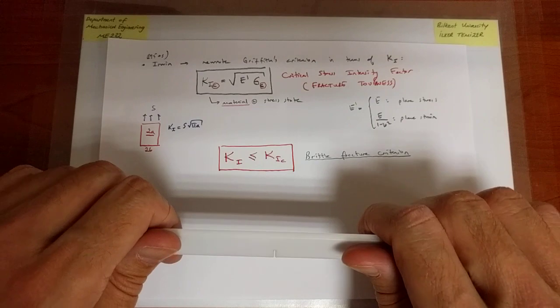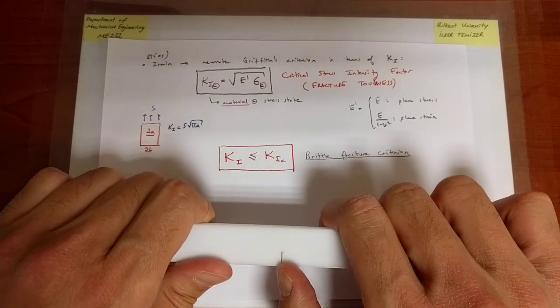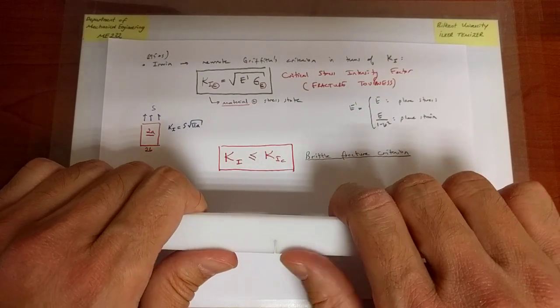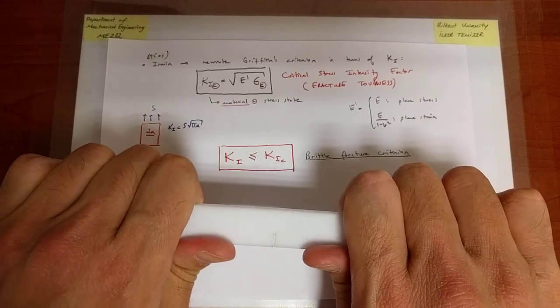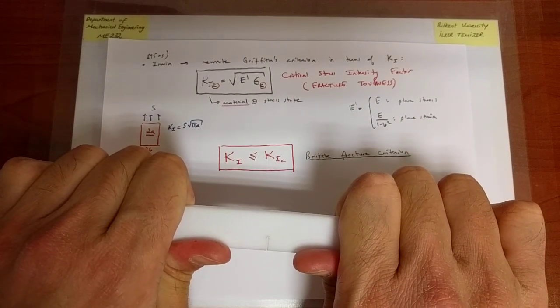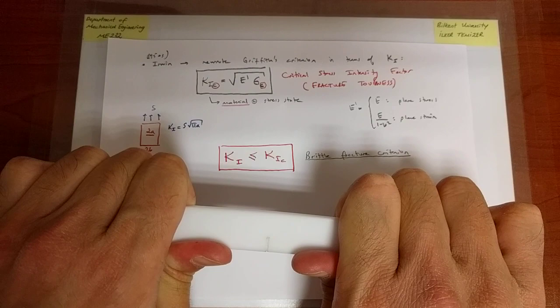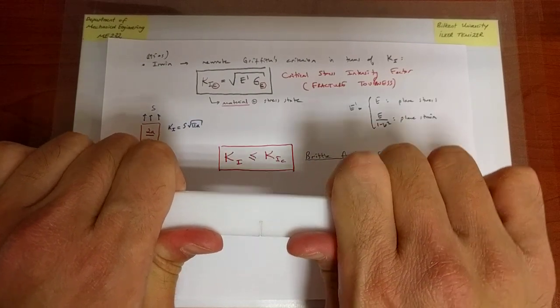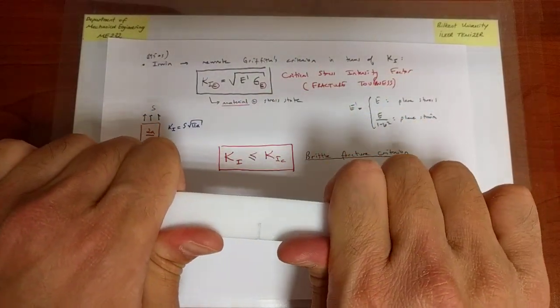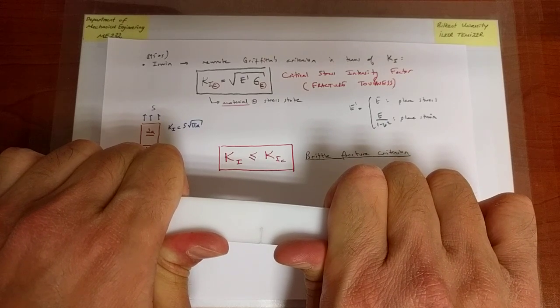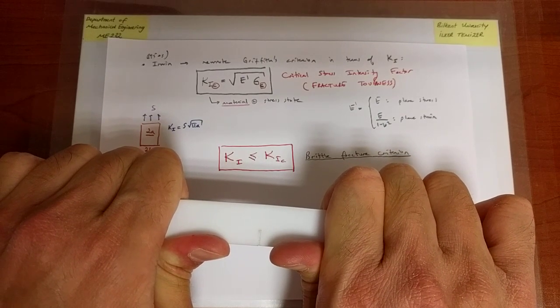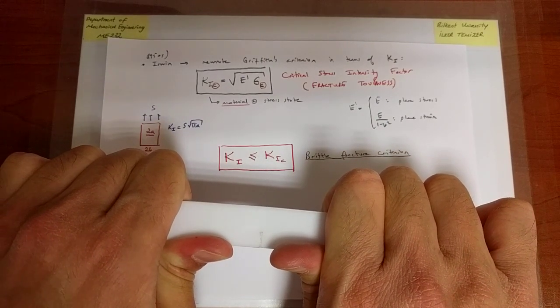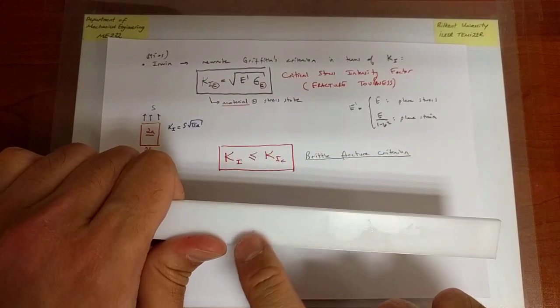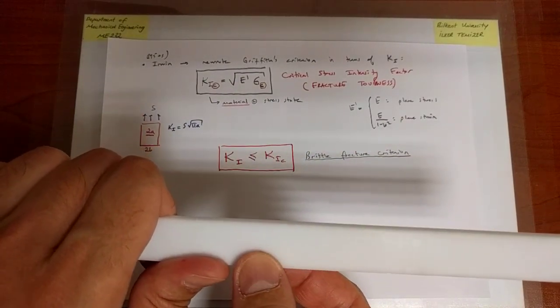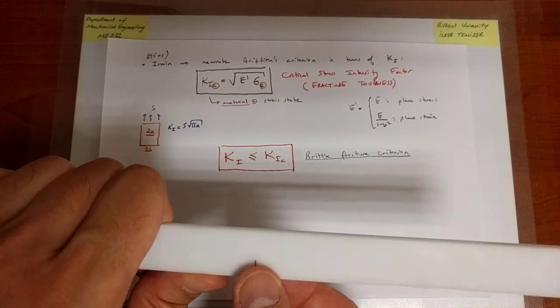So what we are going to say is that the presence of the crack reduces the strength of the structure. Well, how does it do so? First I bend in this direction, and the crack is certainly there, and the force that I'm applying is quite large, but nothing is happening. Well, why is nothing happening? Because there is a solid cross-section here, and that's the effective cross-section of the beam.